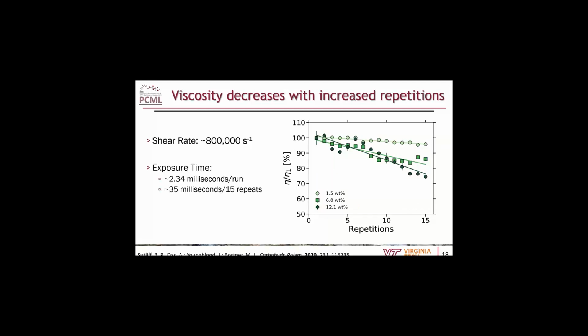If you look at this on a percentage basis, our 12 weight percent is losing about 25 to 30% of its original viscosity as it goes over time, and even our 1.5 weight percent, which is almost indistinguishable from water, loses about 5% of its original viscosity.